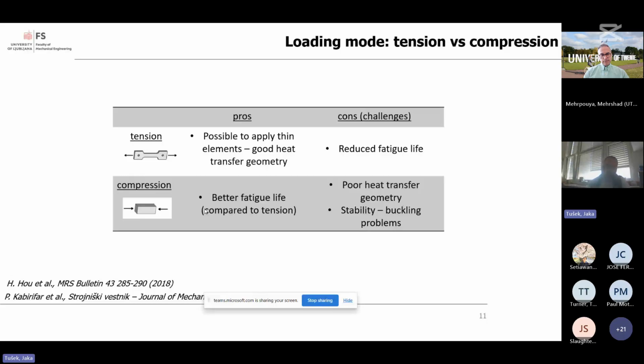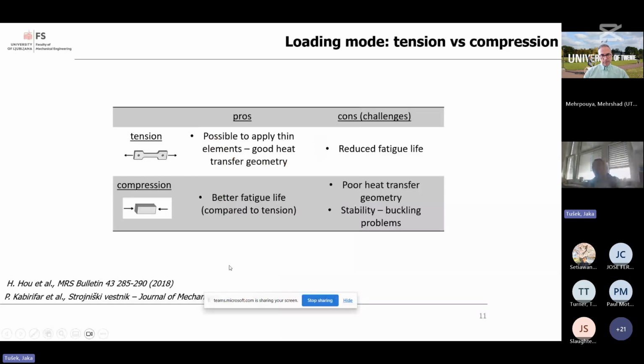Because in tension, as shown here, any cracks or impurities in the material will already grow and expand during loading, while in compression, those cracks and impurities are getting closed, which can significantly prolong the fatigue life. But the problem is that it's impossible to simply compress a thin sheet or thin wire without buckling issues. So it's very challenging to come up with a geometry that can have efficient heat transfer, but at the same time has buckling resistivity.